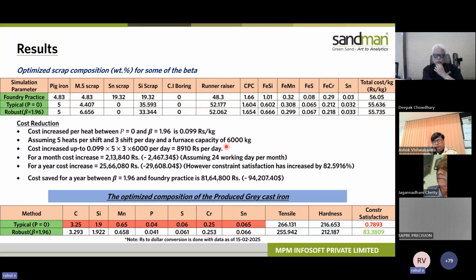But when you take those to a yearly scale, assuming 5 heats per shift and 3 shifts per day, and a furnace capacity of 6,000 kg, the cost goes up to 8,910 rupees per day, and a monthly increase of 2,13,000 and a yearly increase of 25,666. So this is how much the cost will increase from a typical formulation to a robust formulation.